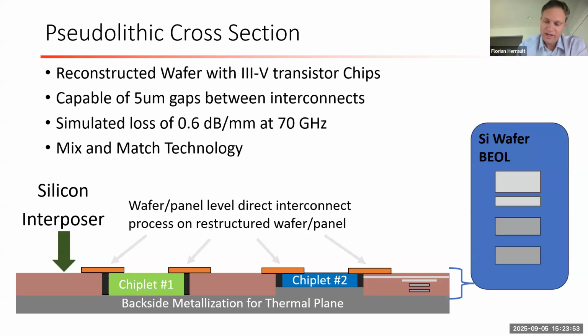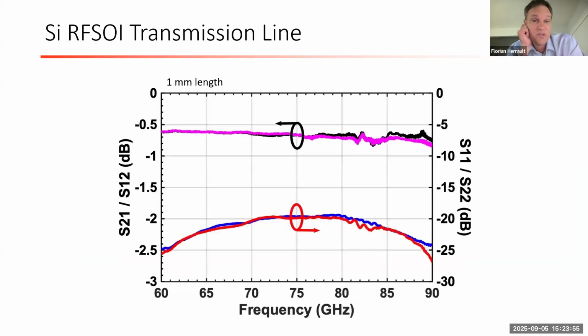And so does this work at RF? Yes, this RF-SOI technology is actually very well suited for RF. This is an example of a transmission line built on the silicon RF-SOI technology, and it measures at 75 gigahertz, about 0.6 dB per millimeter. So this might be 0.1 to 0.2 dB higher than what you can do with gold on silicon carbide, but still very, very well suited for RF high-performance circuit designs.